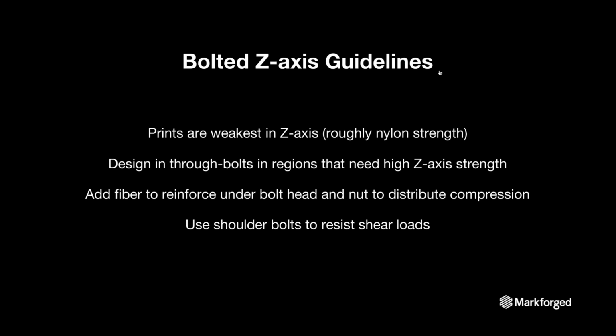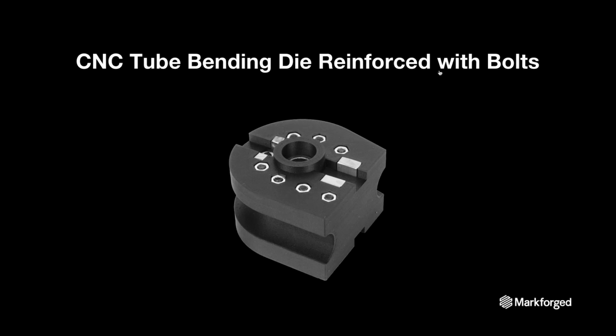So prints in the Z, obviously, are going to be the weakest. Design through bolts in those regions where you need the Z strength. If you need the Z strength in those regions, as well as in the XY, and you can't find the right orientation, this is a solution. Add fiber to reinforce under the bolt and the nut to distribute that compression force, that bearing force, essentially, across the face. This is what we did with the tube bending die.